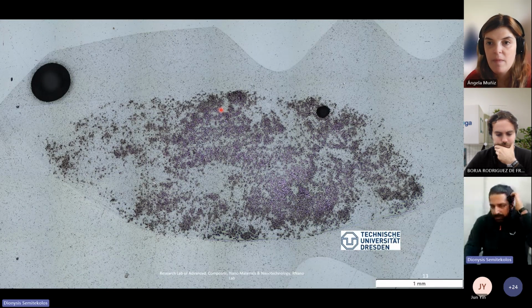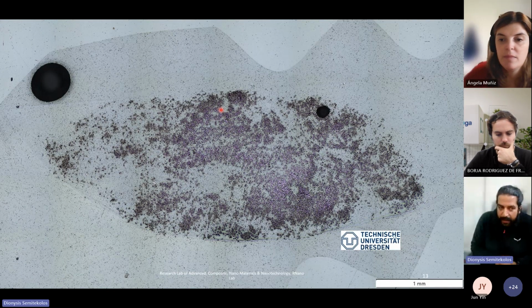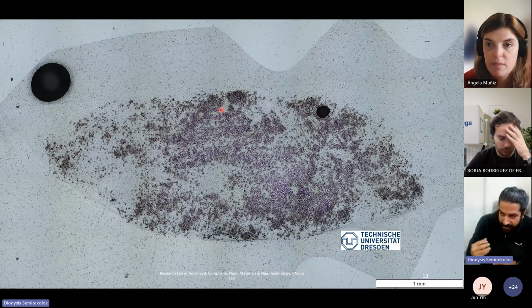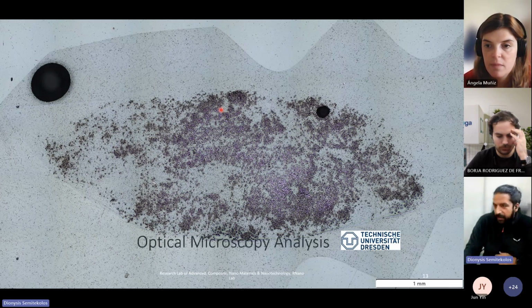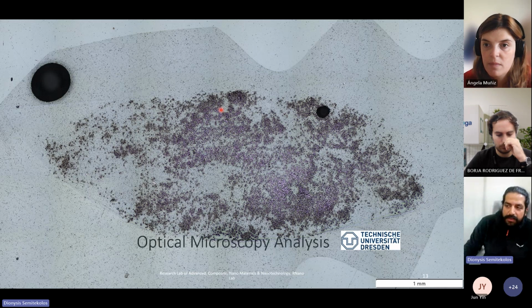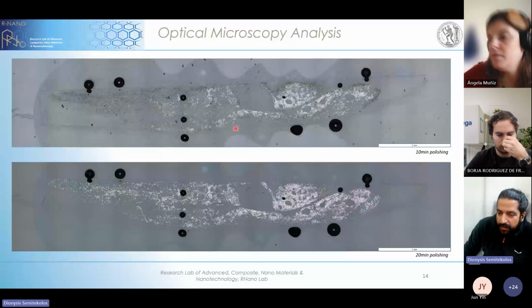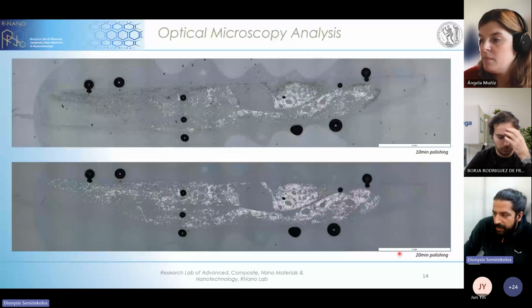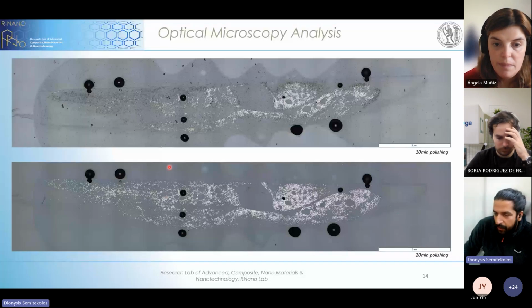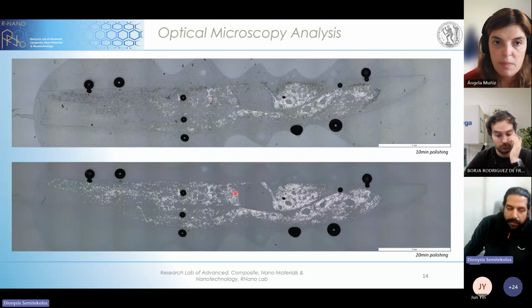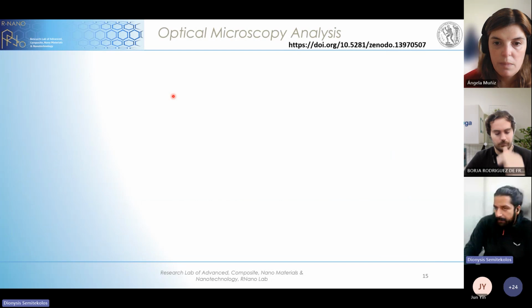Then we wanted to quantify the amount of filaments that we lose after the recycling process, and this is something that we did with the Technical University of Dresden. I have just put these two images here to show you how different a good picture looks like. On the second picture, we see these white spots, I don't want to zoom in because I will lose the slides, but these white spots represent single fibers, and you see here that with 10 minutes polishing, we have these black speckles, which would affect our fiber count.